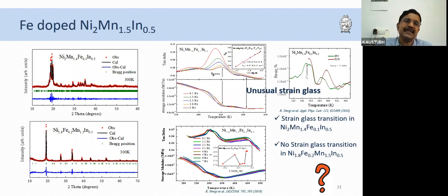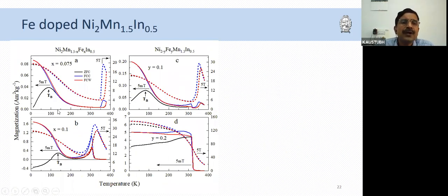So we looked at magnetization measurements on these alloys, and I'm showing you only 2 examples from both series. This is 0.075 and 0.1 in the MnFe case, and you can see the martensitic transition is disappearing, and the temperature is decreasing. The second thing that you see is the magnetization going towards negative, a sort of magnetically compensated state happening here, and then there is a reversal of magnetization. Whereas in the case of NiFe, you can see that the antiferromagnetic ground state has changed to a ferromagnetic ground state with a TC of around 330 or 340 Kelvin.